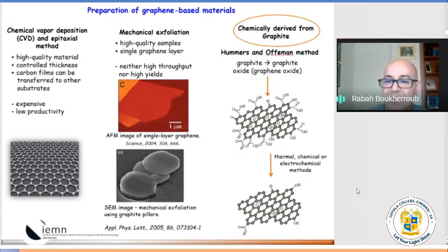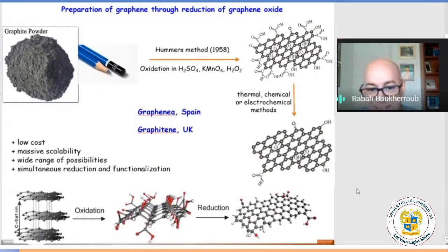People will call whatever graphene, although as soon as you exceed a certain number of layers, a few layers, then you lose the properties of real pristine graphene, like CVD graphene. Then you should not consider that as graphene or reduced graphene anymore, but it's graphite-like material. So you see, this is just breaking up the graphite sheets from graphite oxide through oxidation. So you make something which is negatively charged, so you can easily disperse that in water. However, you lose all the properties of the graphene.